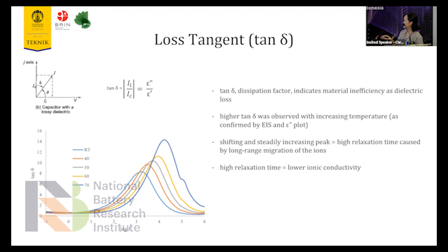And shifting and steadily increasing peaks means high relaxation time because the long migration of the ions causing lower ionic conductivity because it is taking too long to move.